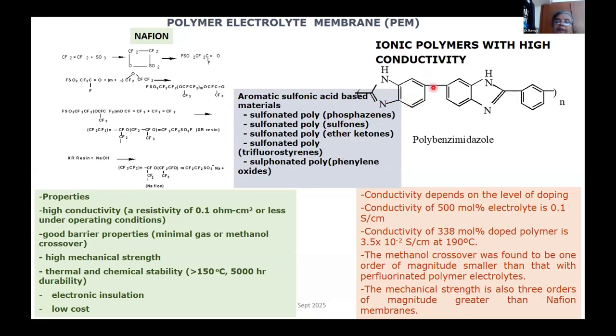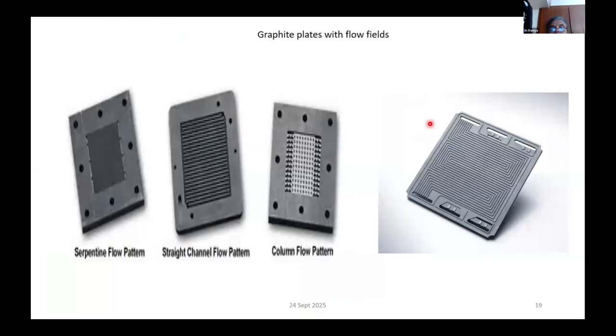The only other membrane to make it to commercial is the polybenzimidazole based membrane, but this operates at medium temperature, like the phosphoric acid PAFC fuel cell. Here also phosphoric acid is doped onto this membrane to achieve good conductivity. This membrane has very good strength, and it is what people call HTPEM, high temperature PEM fuel cell. It operates around 160 to 180 degrees centigrade, so this membrane can also be used. If you want to start at low temperature, of course you have to go to Nafion.